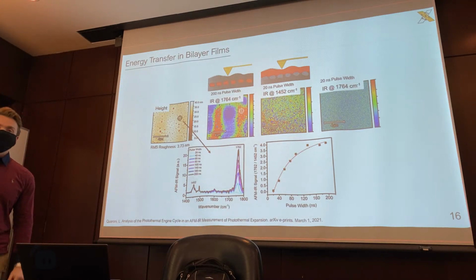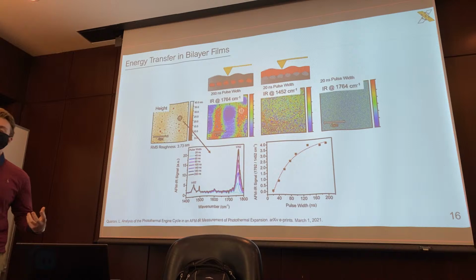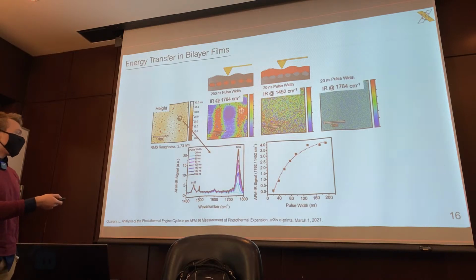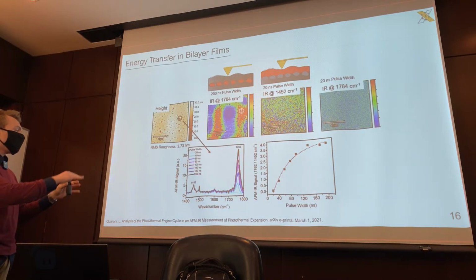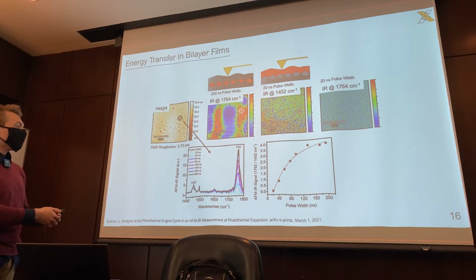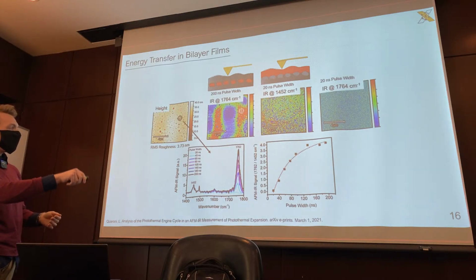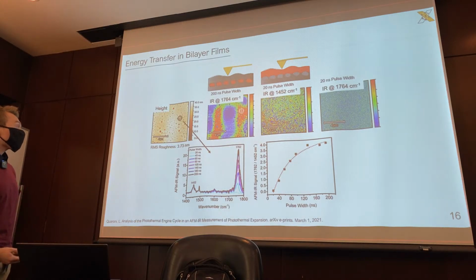So this highlights that our material at the bottom is simply not being excited efficiently, so we're not able to detect it. Here I've also plotted the AFMIR signal in terms of the ratio of PLA to polystyrene as a function of pulse width, and you can see how that behaves there.